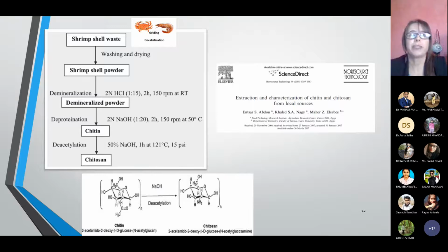The second step after demineralization is deproteination. Here we will remove the protein from this material. It was performed using alkaline treatment with sodium hydroxide solution. This treatment was repeated several times as well. The number of baths depends on the clarity of the solution. Here we will eliminate the color. So we will do this step many times until the color disappears.